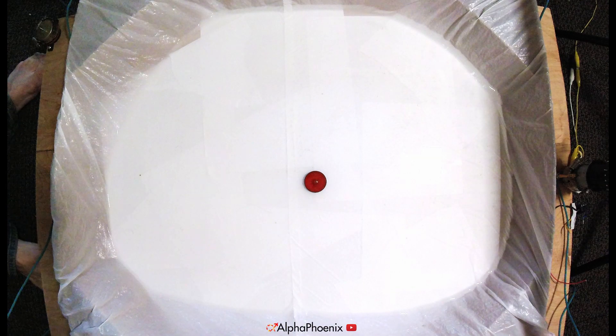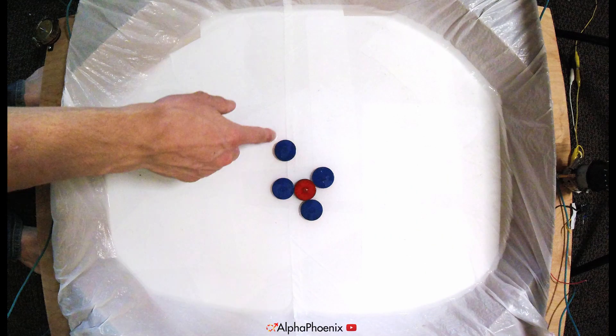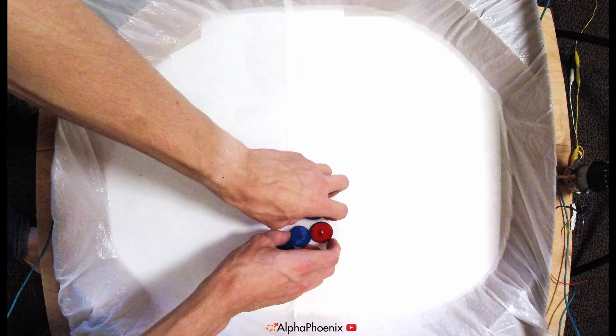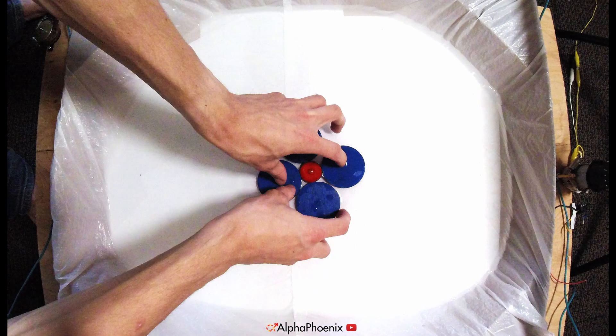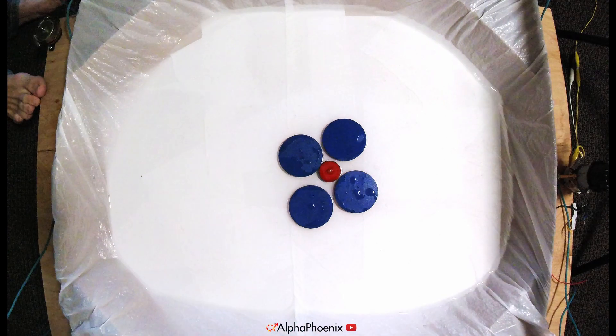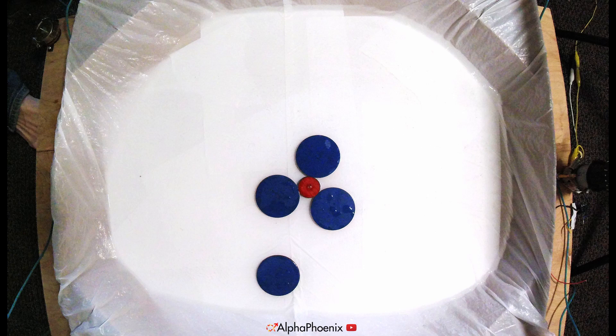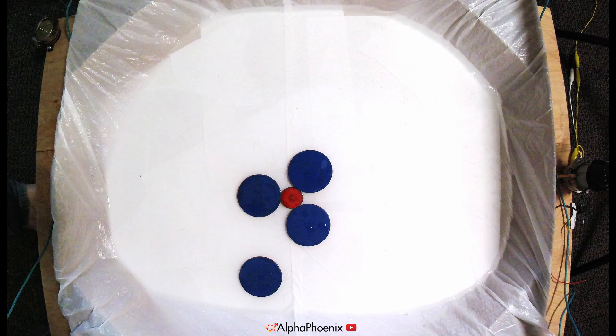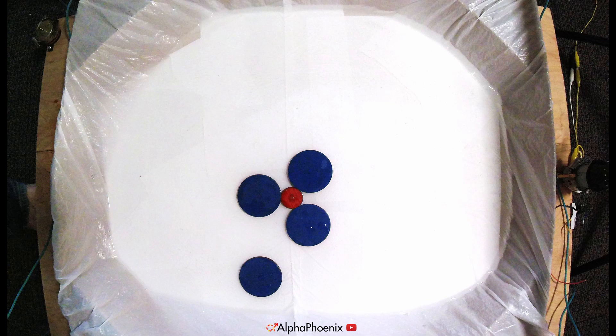And a square checkerboard pattern means that the structure has an equal number of reds and blues in it so it works. However, if we make the blues larger and larger, they repel each other and eventually only three blues can fit around a single red. Meaning that the smallest repeated unit turns into a triangle. And we get this new pattern made of triangles and hexagons.